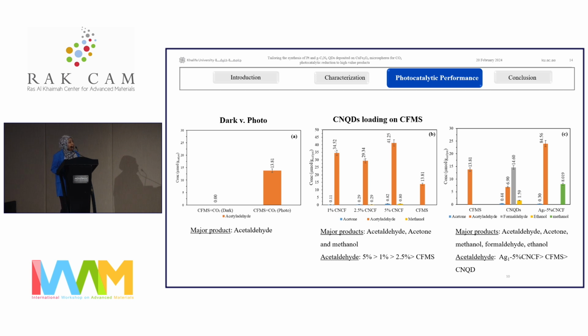Then we moved on to testing the copper ferrite microspheres. So we did the reaction in dark condition and illuminated condition. In the dark condition, no products were formed, while in the illuminated condition, we formed acetaldehyde. Then based on that, we decided to prepare the nanocomposites by depositing the graphitic carbon nitride on the copper ferrite using different ratios. And then we observed that as we increased the loading, we produced a higher yield of acetaldehyde in addition to acetone and methanol as well.